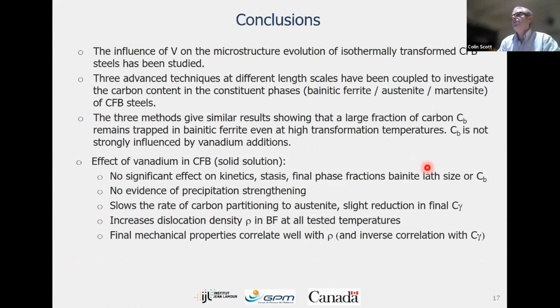So conclusions, we've studied the influence of vanadium on isothermally transformed CFB. We used 3 different techniques at very different length scales. I didn't mention that, but you're looking at cubic millimeters in the HEXRD. In the TEM with the foils, you're looking at the micron and submicron type scale. And with the atom probe, obviously, you're at the nanometer range. So all those 3 techniques give the same basic result.